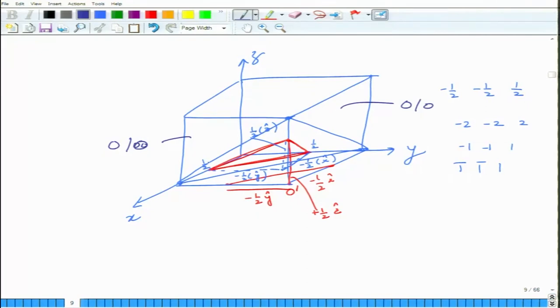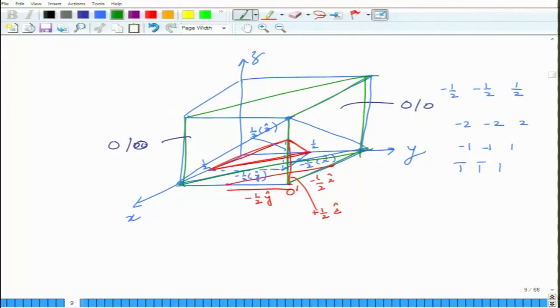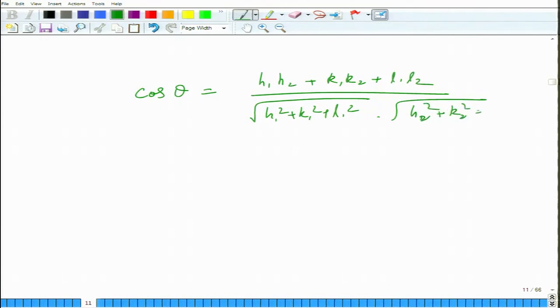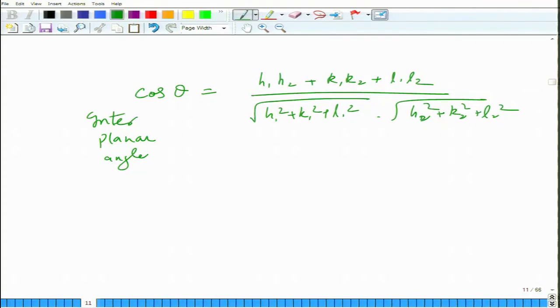You can also find the angle between two planes. For cubic systems the inter-planar angle is given as: cos θ = (h₁h₂ + k₁k₂ + l₁l₂) / [√(h₁² + k₁² + l₁²) · √(h₂² + k₂² + l₂²)]. This is called the inter-planar angle. Note that these formulae are only for cubic systems — for tetragonal or orthorhombic systems the relations are different.